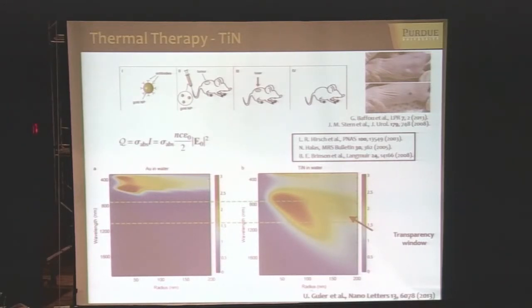In this case, they use gold nanoshells. The reason why they use these nanoshells is because if you take a gold nanoparticle, we know the resonance is around 540 nanometers. But the biological transparency window is actually between 800 to 1100.